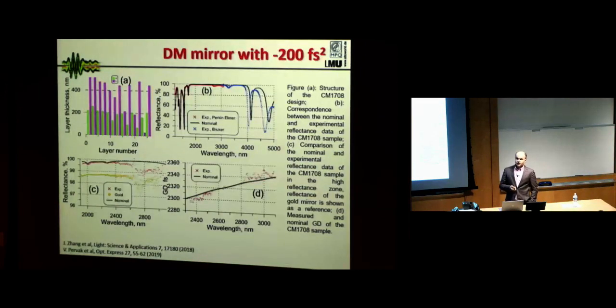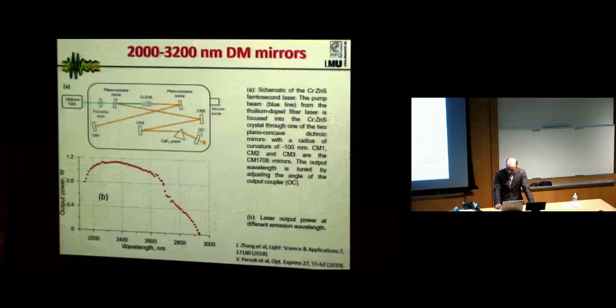When we move to the infrared range, each wavelength region has its own problems. For example, when you try to generate something in the infrared range, especially around 3 micrometers, there is water absorption. What happens to our multilayer structure is that you produce a mirror, it looks nice, but as soon as it stays in a humid environment, like air here, it absorbs water from the air, and you have huge absorption. By using a special design, we were able to produce mirrors with very small water absorption in this region. Here the red color shows the reflection curve for the mirrors, and here is a GDD measured in this wavelength region. It's very nice for the mirrors